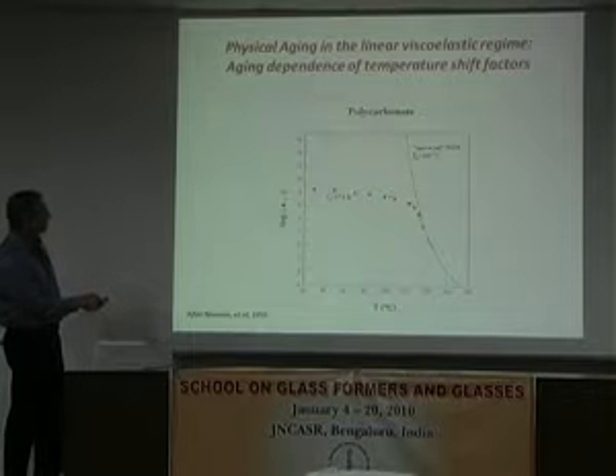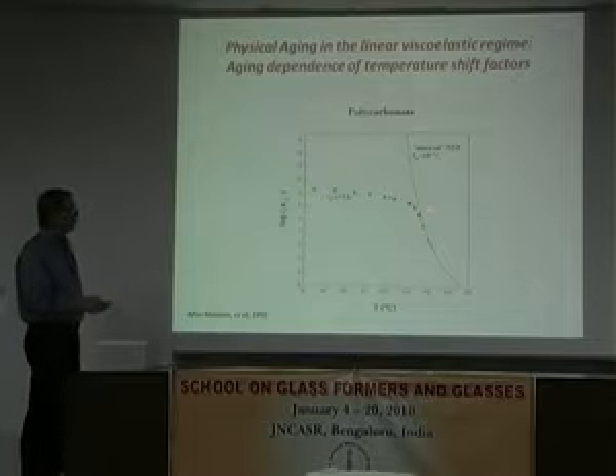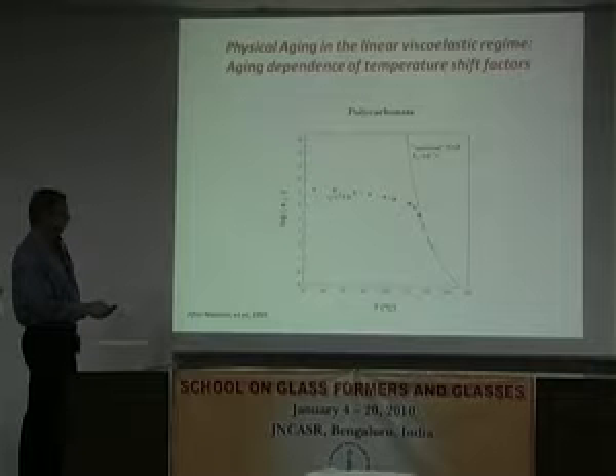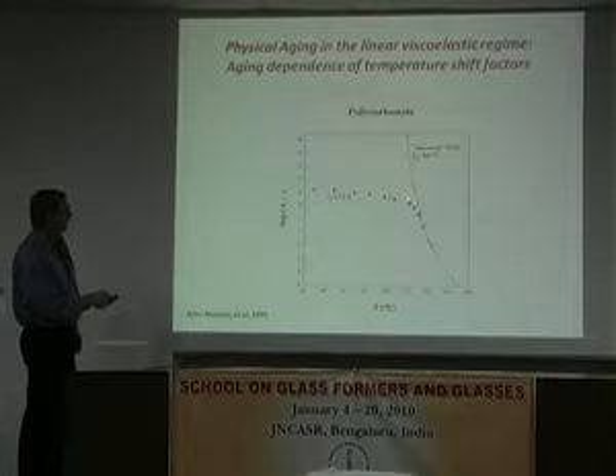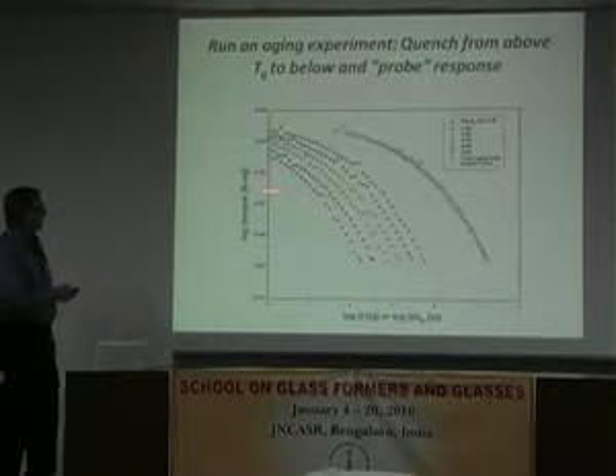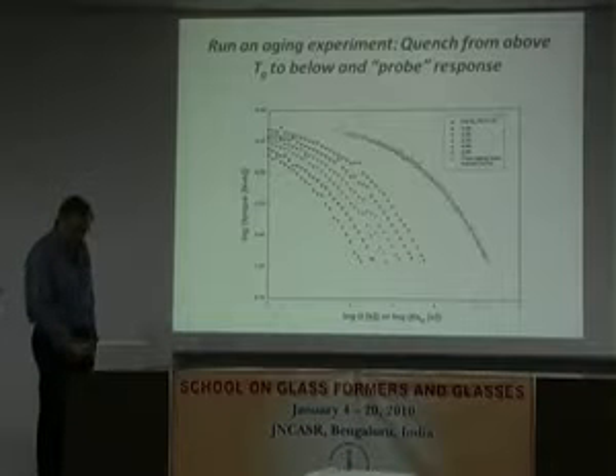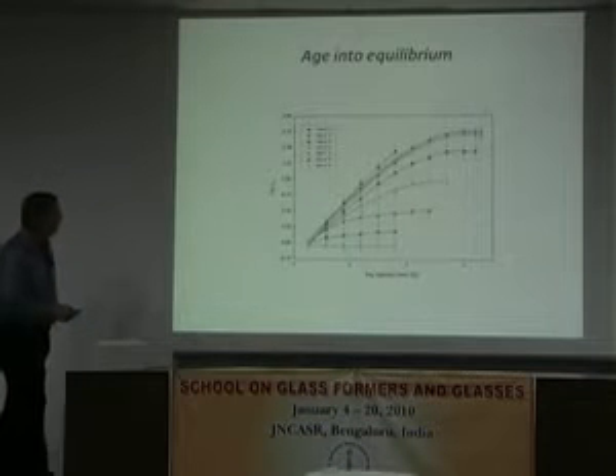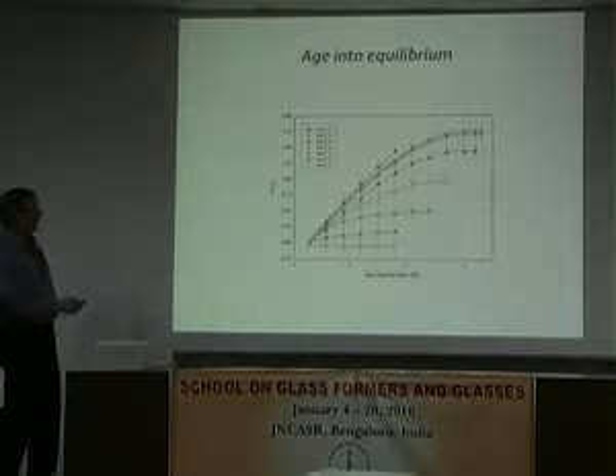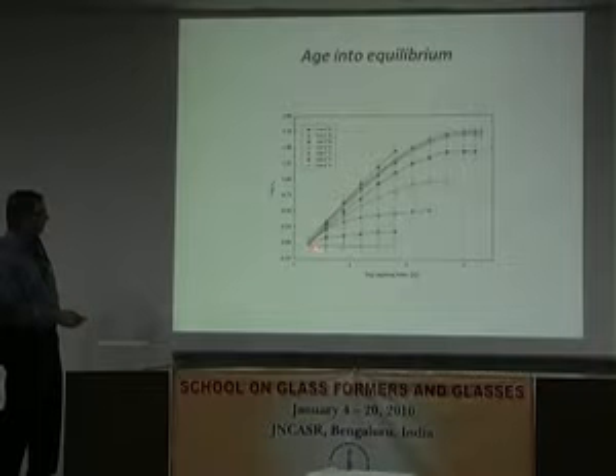As I indicated, what we're going to try and do is be down here somewhere, as low as we can go and still be able to get into equilibrium. Of course, if we follow this line, it's going to be a really long time before we get into equilibrium. So we're going to do this and see how far we can get. We do these aging time superposition experiments and get a master curve, just so we know we have that kind of behavior. We also do aging into equilibrium at different temperatures. The Tg of this material is around 140 degrees centigrade, roughly. Since the first aging time is somewhere around a half hour, it's already aged into equilibrium, so it doesn't age.